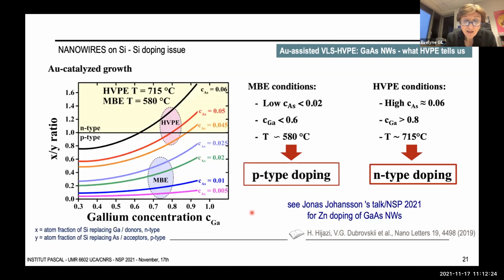And the conclusion is that it will depend on the arsenic to gallium ratio in the droplet. As a matter of fact, thermodynamic calculations of the fraction of silicon atoms replacing gallium or arsenic in the crystal show that for low concentration of arsenic in the droplet, which is the case in MBE, silicon atoms replace arsenic in gallium arsenide rather than gallium, just because as the droplet contains very few arsenic atoms, it enhances the reverse transfer from solid to liquid, which is not the case for stoichiometric vapor-solid growth. And HVPE, which provides the highest arsenic concentration in the catalyst droplet, results in usual n-type doping by replacement of the gallium atoms.